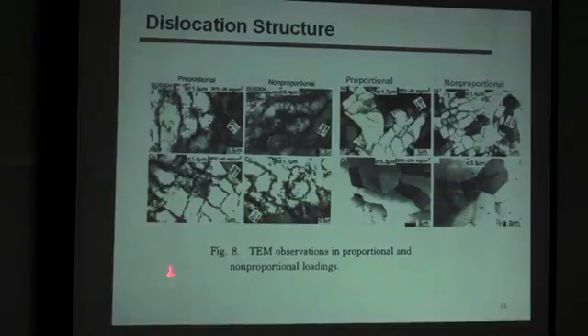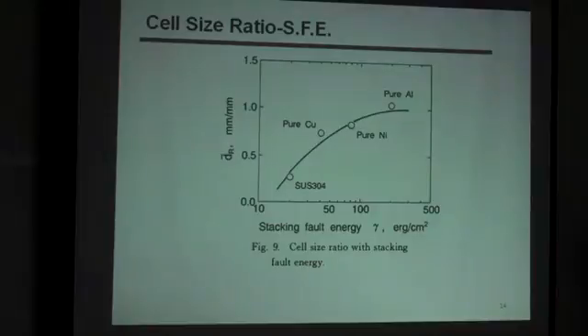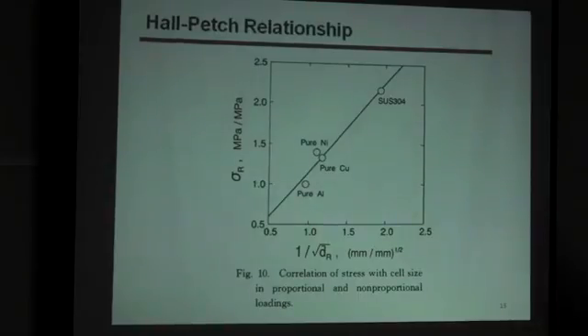And we observe the dislocation structure by TEM. Under cyclic loading, we always find a cell. A very clear cell we found in aluminum, and we also see it in SUS304 stainless steel. And then we plotted the mean cell diameter against the stacking fault energy. So you can clearly see that low stacking fault energy has a small cell size. This is the Hall-Petch relationship. The gradient is minus 0.55. So most of the main cause of the additional hardening comes from the reduction in cell size.